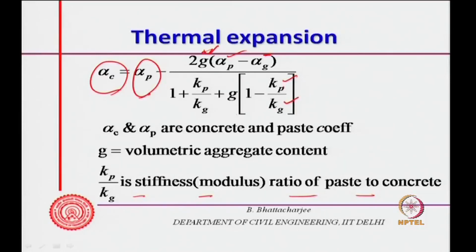So, these factors, the modulus of elasticity, volume fraction, and paste and aggregate expansion coefficients, all affect the coefficient of thermal expansion of concrete.